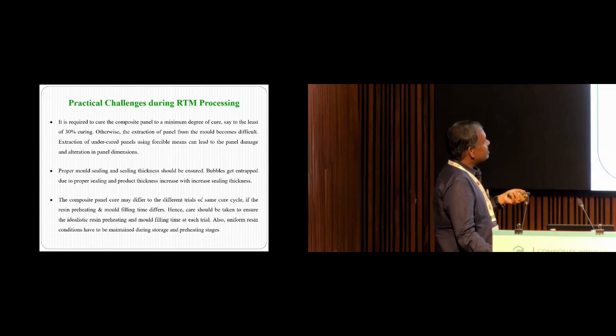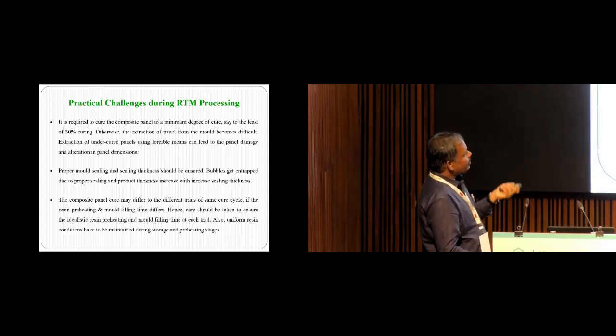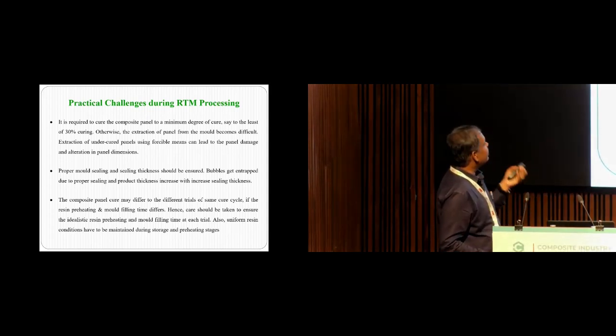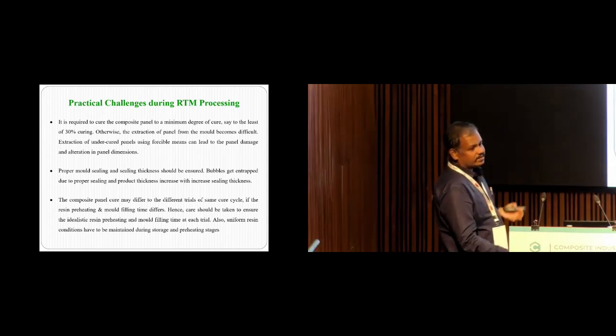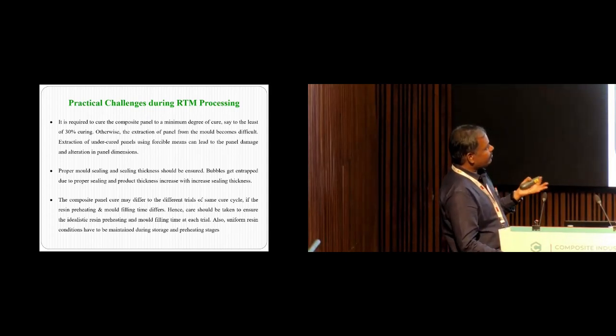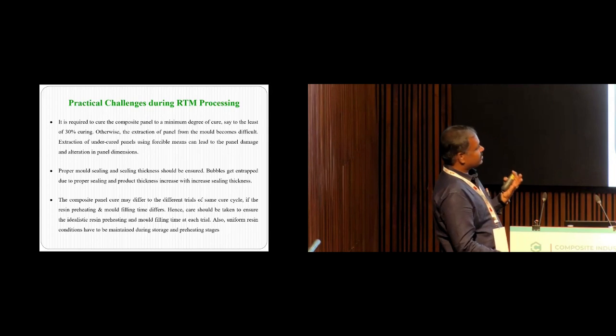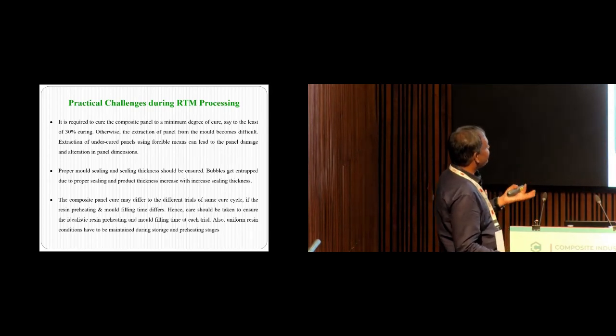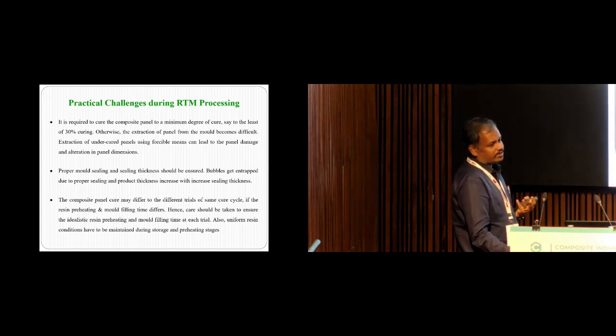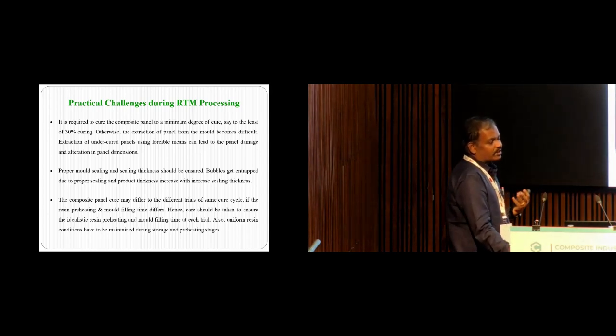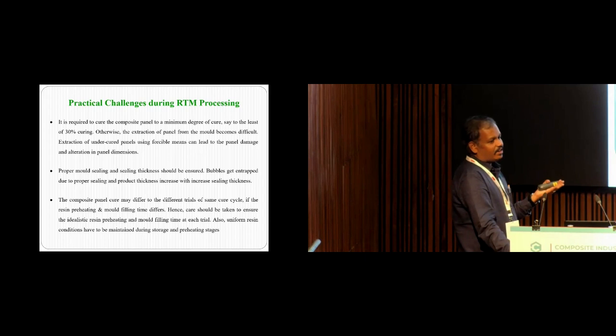Obviously it is required to cure the composite panel to a minimum degree of cure, say at least 30% of curing. Otherwise, the extraction of the panel from the mold becomes difficult. Extraction of under-cured panels using forcible means can lead to panel damage and alteration in panel dimensions. Obviously we know the strictness in the dimensionality required for aerospace grade composite panels.